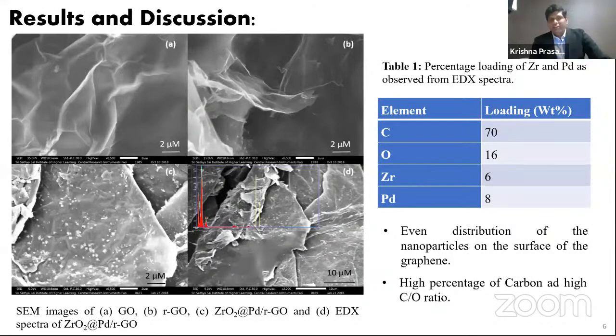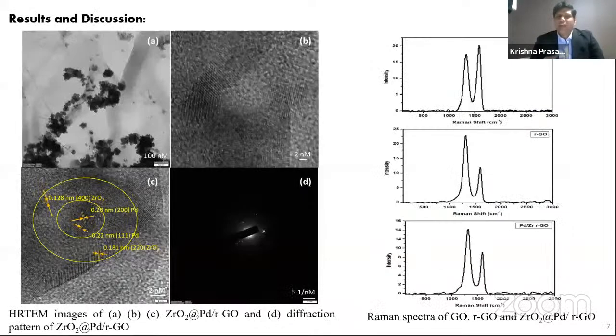So coming to the characterization, we first recorded scanning electron micrographs of these materials, and we found that the synthesis of RGO was successful. Subsequently, we also found that there is an even distribution of the nanoparticles on the graphene. Energy dispersive X-ray spectroscopy was performed to know the percentage loading, and the graphene was found to have a very good carbon to oxygen ratio, and also the nanoparticles were distributed evenly. We also wanted to check the core shell morphology of these particles, and hence we did high resolution transmission electron microscopy, and we found that the particles have a core shell nature, and it was confirmed from the lattice planes that the core is palladium and the shell is zirconium oxide.